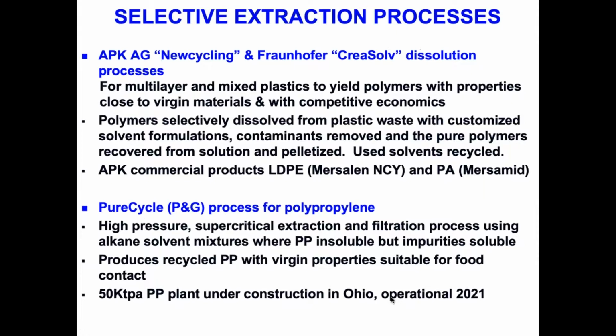Some selective extraction processes, APK Newcycling and Fraunhofer CreaSolv dissolution processes, both in Germany. These are for multi-layer and mixed plastics to give properties close to virgin materials, and they claim competitive economics. The polymers here, this is a little different from the last two processes. The polymers are selectively dissolved from the plastic waste with customized solvents. This removes contaminants, and the pure polymers are recovered from solution and pelletized, and the solvents are recycled. So APK already has commercial products here for LDPE and also polyamide.